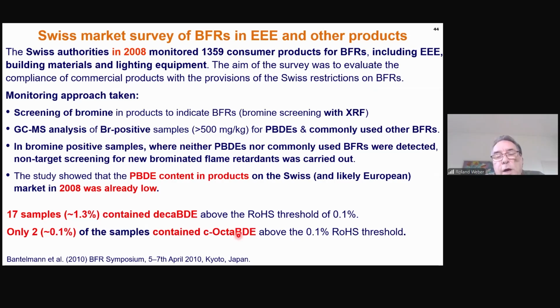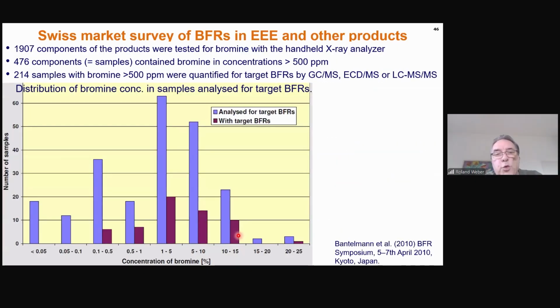So already in Europe in 2006, the RoHS directive included the DecaBDE, and therefore industries started to phase out. This kind of information also is quite helpful for you when doing such monitoring. Overall, the Swiss market survey analyzed 1,900 components. This means they screened different parts of plastics in products. In total, 470 components contained bromine above 500 ppm, and 214 samples were then quantified for the PBDEs.